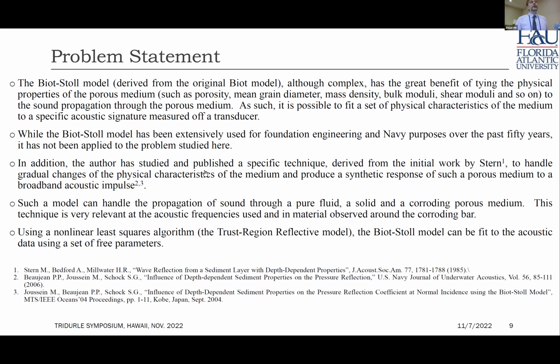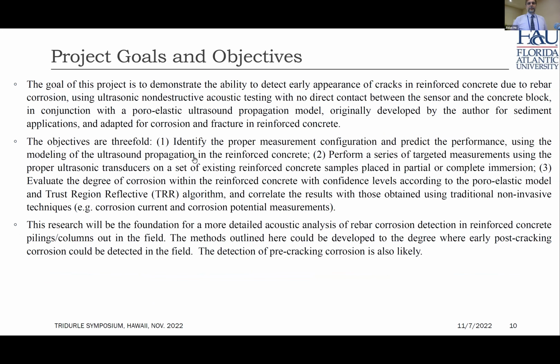Now, knowing this model exists, we can adapt the model to reinforced concrete problems and actually tie this to a nonlinear least square algorithm, in our case, the trust region reflective model I selected, to fit the parameters of the Biot-Stoll model, which are physical parameters of the rebar and concrete, to what we actually measure. In short, the objectives are threefold: one, identify the proper measurement configuration and predict the performance using modeling of the ultrasound propagation in the reinforced concrete.